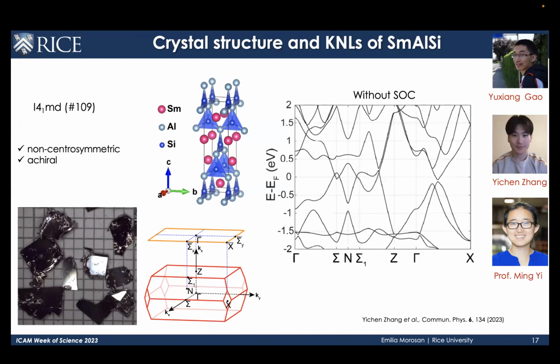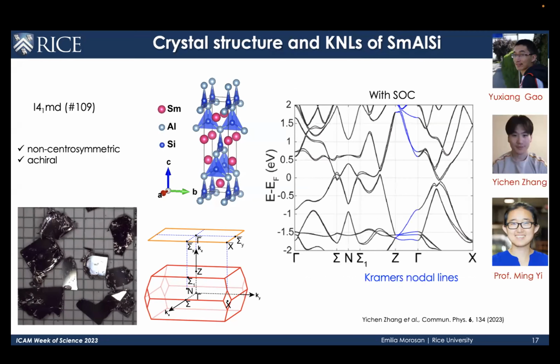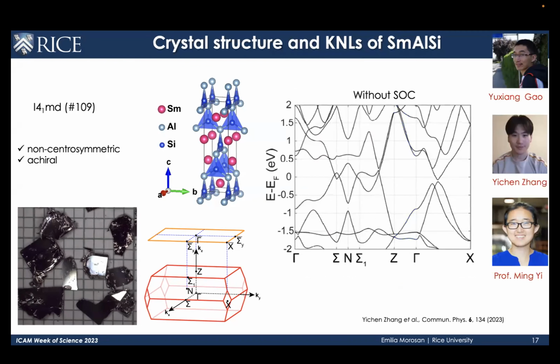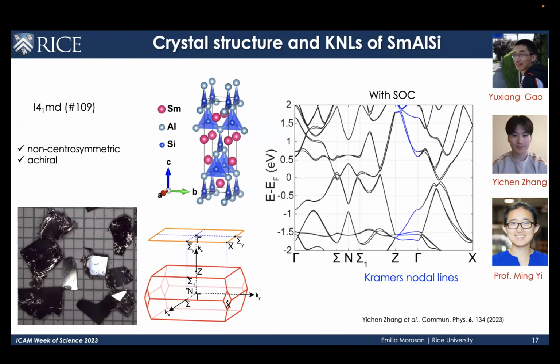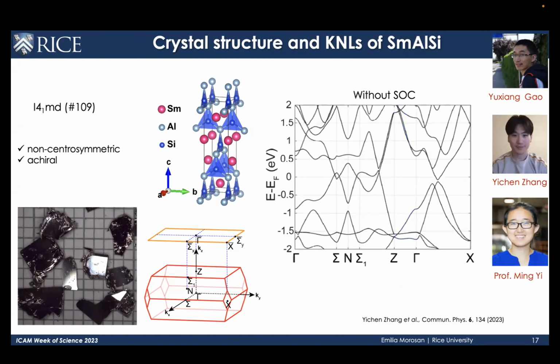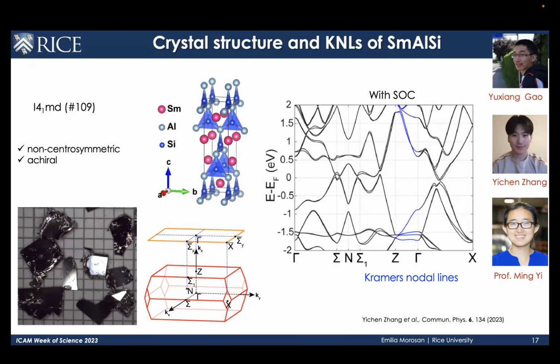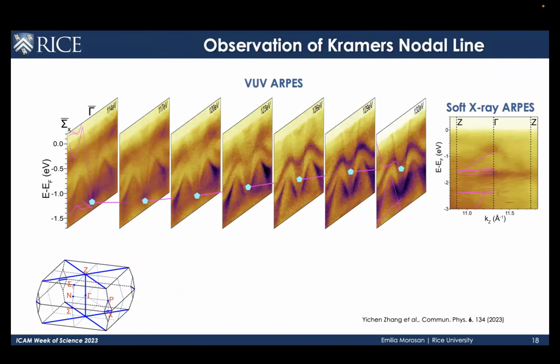Here's the band structure without spin orbit coupling, where you might not be able to see exactly what I'm after, but let me toggle back and forth between the band structure with and without spin orbit coupling. And what you notice is that the bands are non-degenerate nearly everywhere except along the gamma Z line with spin orbit coupling. So the gamma Z lines remain degenerate even with spin orbit coupling, while the degeneracy is lifted everywhere else. So here's the ARPES that shows this point moving up in energy as you do.